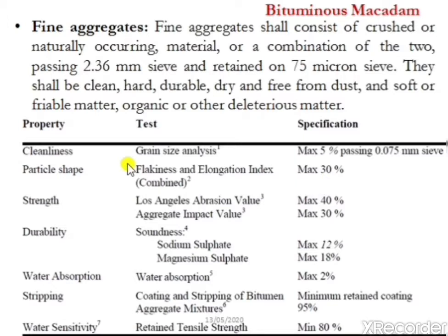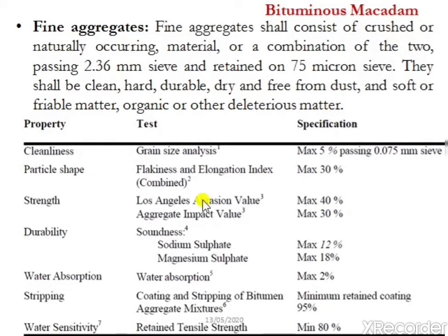To determine the strength of the aggregates, we have the Los Angeles abrasion value test and the impact test. The values of Los Angeles abrasion and impact test should be within 40% and 30% respectively. If the value of abrasion is more than 40%, then the materials are not suitable in the construction of bituminous material. The materials will be soft if the value is more than 40%. Similarly, if the aggregate impact value is more than 30%, then the materials can't be used in the construction of the pavement.